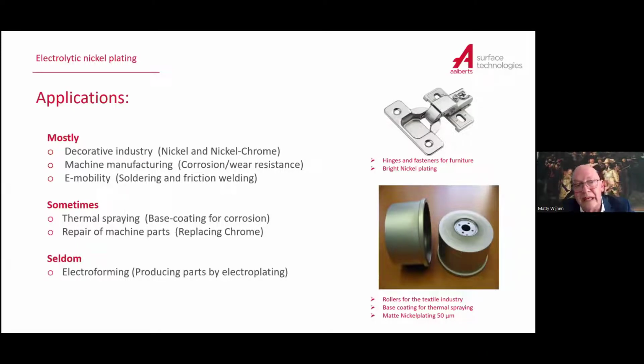Another application is base coatings in the plating industry, just like we have for underlayers of chrome, or chrome, of course, but also on gold and silver, and also on thermal spray coatings. The thermal spray coatings are very porous, and to make sure that there's no under-corrosion, you put a nickel layer underneath them. Or you see it as repair for machine parts, where it replaces chrome, but not for the hardness or the abrasive wear resistance, but for the toughness, the adhesive wear resistance.